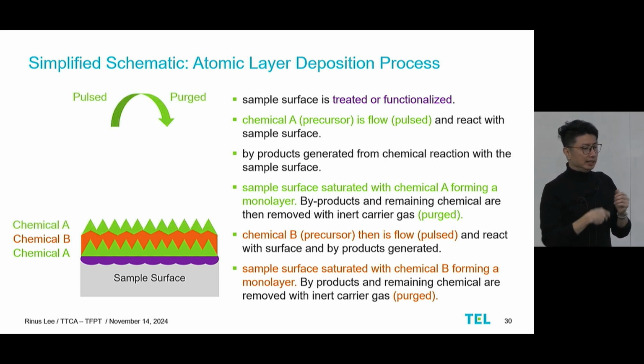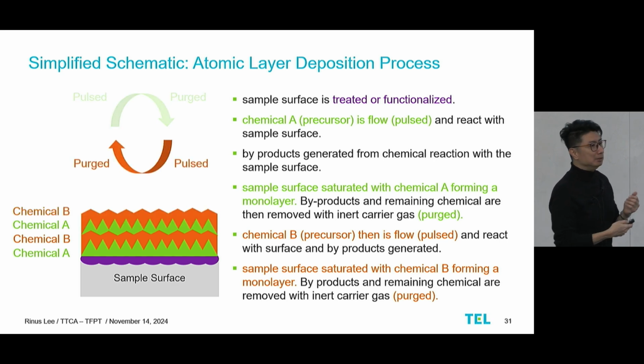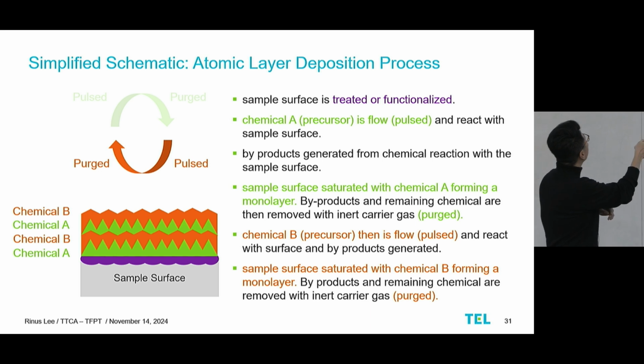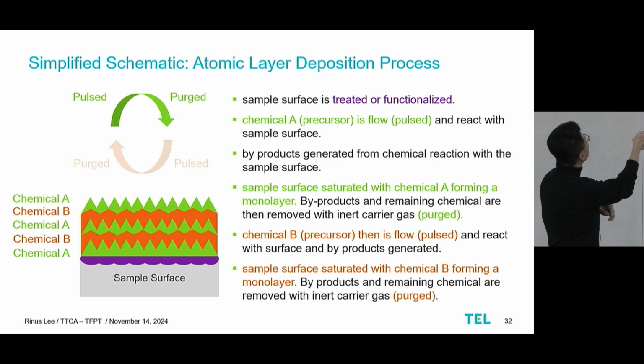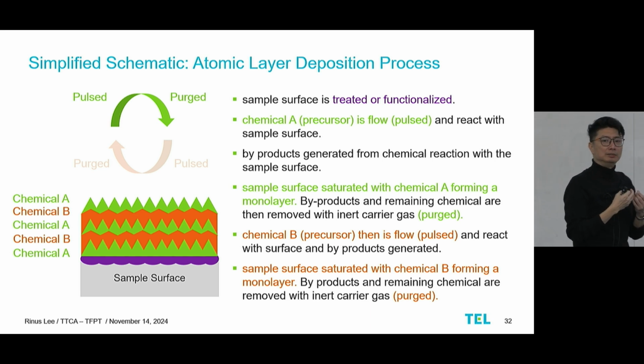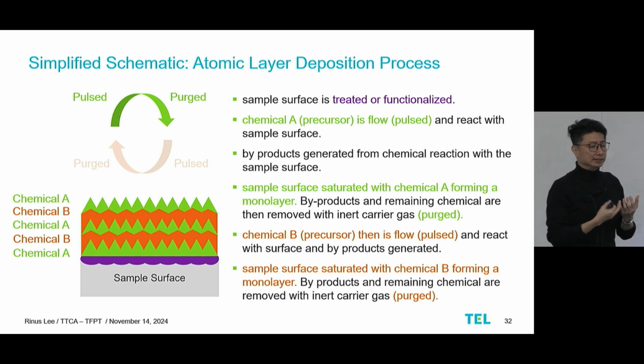And by doing this in a sequential manner, by pulsing, purging chemical A, pulsing, purging chemical B, you could start to increase the thickness of the films that you want. And this is in a very controlled manner because there's no way for chemical A to grow any thicker than the sites that are available for it to react. So what I'm saying again is, for example, chemical B, these are all the sites for chemical A to react. When chemical A comes down, it will just react with all these sites, and once they are all passivated or reacted, any more chemical A coming down would not react, so the thickness will not increase. So this gives us angstrom level process control without sacrificing precision.